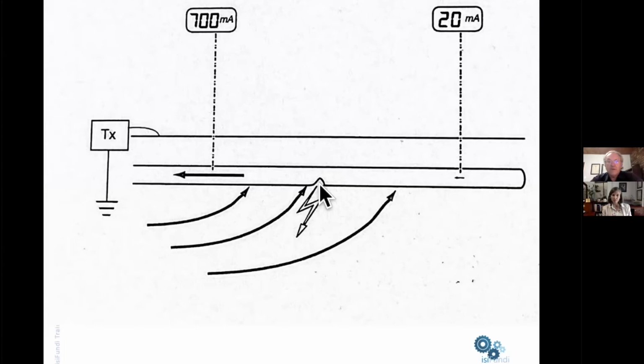It could represent quite a wide area of poor coating, or it could be, for example, a foreign service contact, which is similar to a coating defect in that it causes an unwanted current drain on the pipeline. And you can see that in this situation, you have a significant change in the current level in the pipeline, from 20 milliamps on the right-hand side of the picture to 700 milliamps on the left-hand side, showing us that we've got a significant loss of current in between.